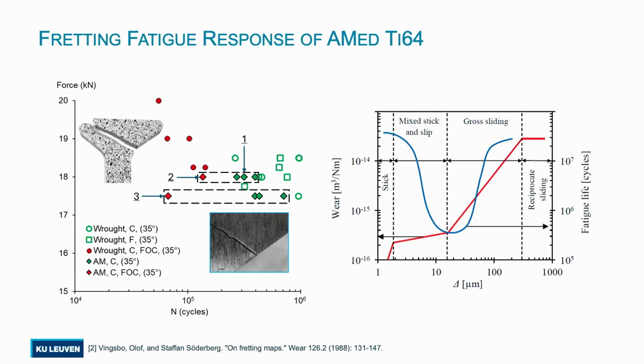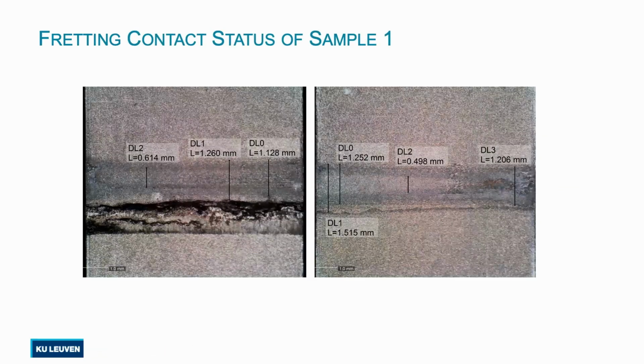And that's the reason that for wrought material, if you overload the sample, so if you apply higher load levels, there wouldn't be any damaging. That's why the crack initiates there. But for these optimum 2 load levels, the reason that we had these 2 failures should be investigated. So I'm going to talk about 3 of these failed samples.